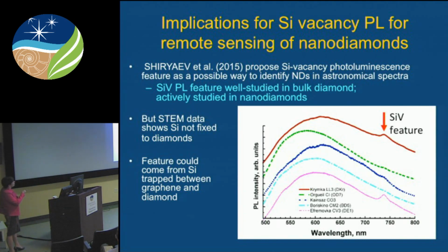All right, so why should you care about that single silicon atom? Because if you want to go hunting for the nanodiamonds in an astrophysical environment, you might want to look for an absorption or luminescence signature from the silicon atoms. The nanodiamonds intrinsically are not active in the IR, but you can get a luminescence signature from a silicon vacancy impurity if it's incorporated into the nanodiamonds.